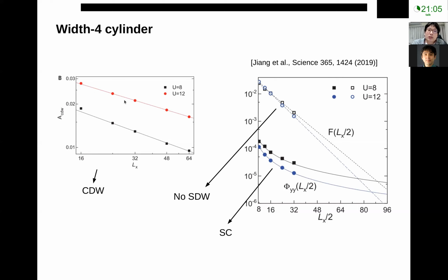So there's still a charge density wave, but more importantly, now the superconducting correlation becomes power law decay. This is pretty encouraging, because now we get a more consistent result with experiment: only charge density wave, and kind of quasi-long range superconducting order.